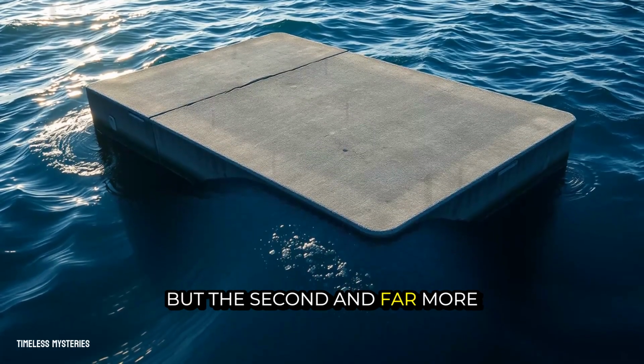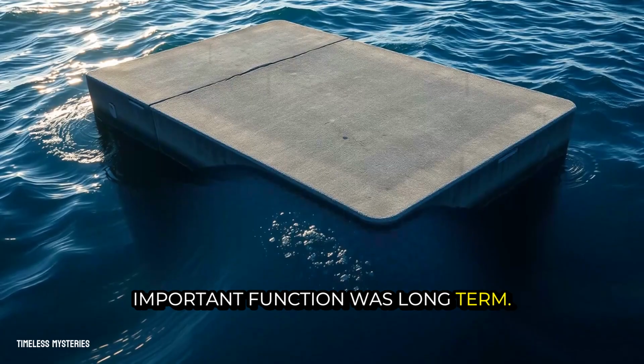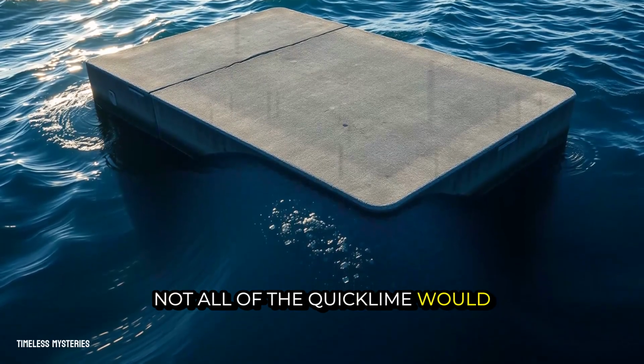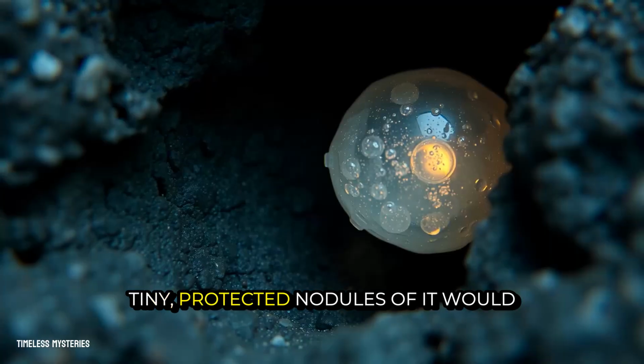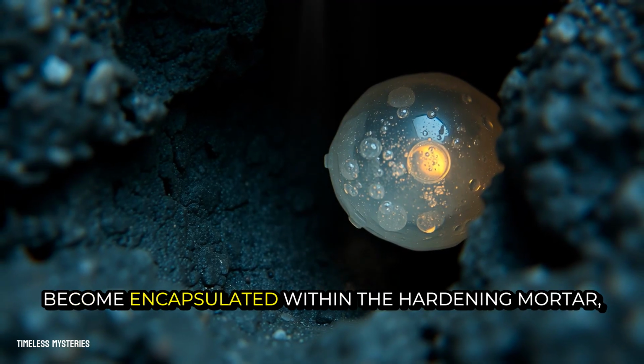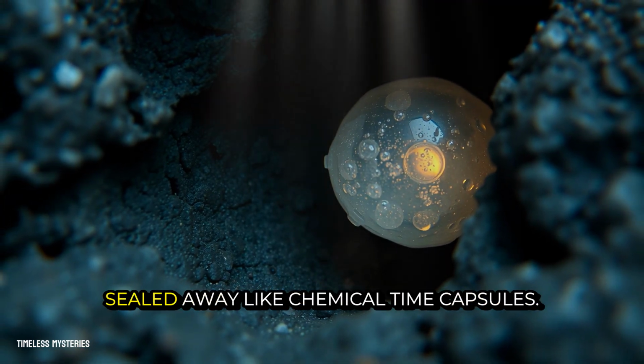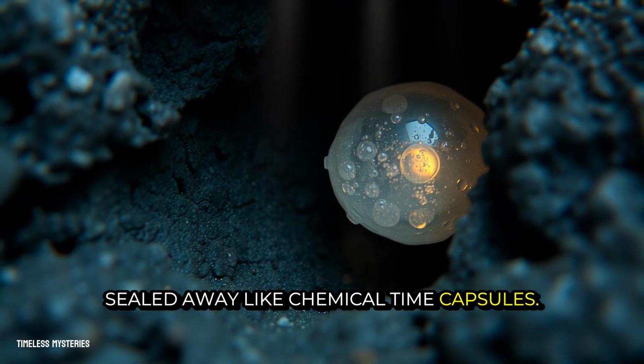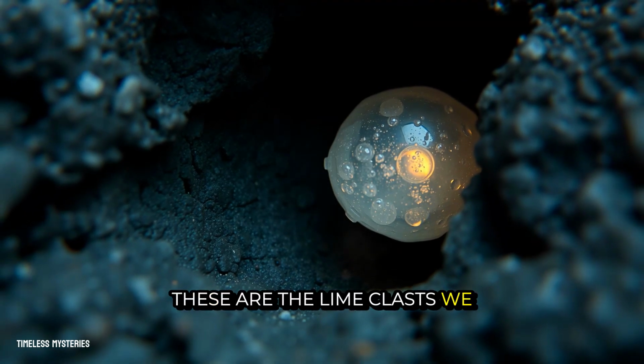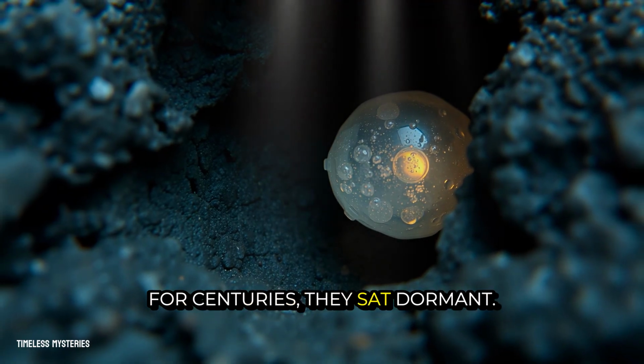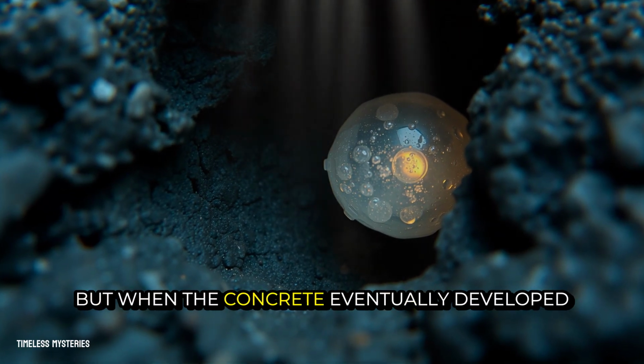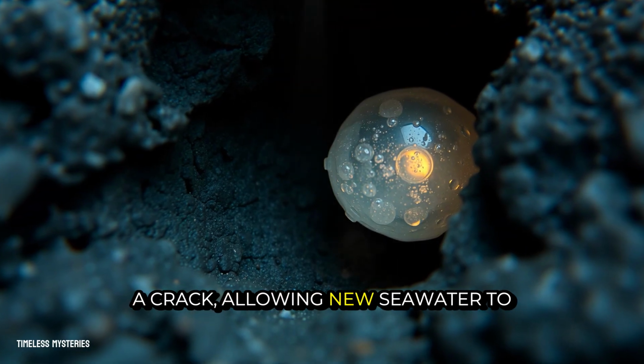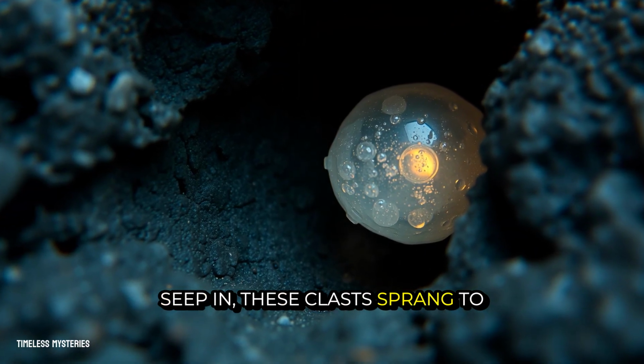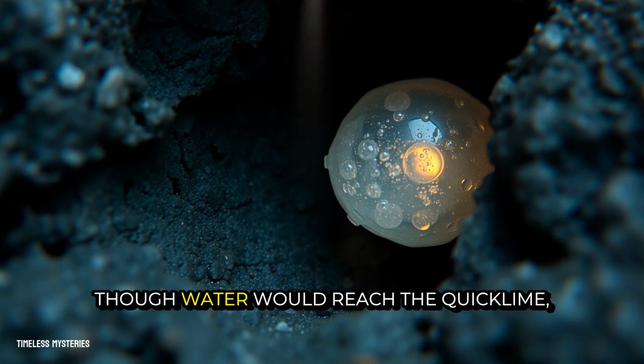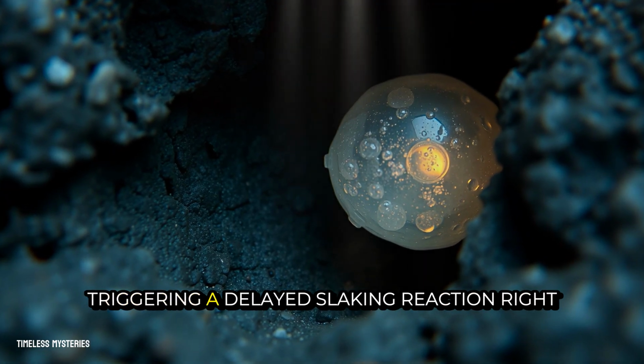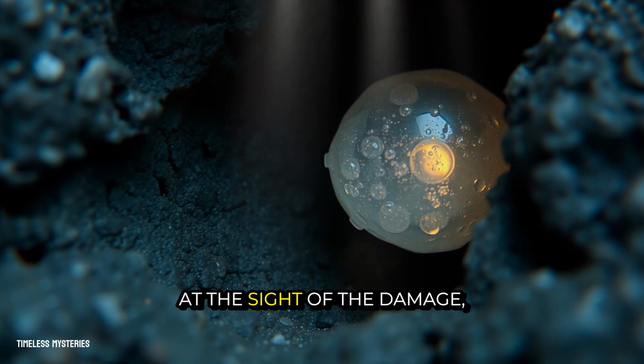But the second, and far more important, function was long-term. Not all of the quicklime would react immediately. Tiny, protected nodules of it would become encapsulated within the hardening mortar, sealed away like chemical time capsules. These are the lime clasts we see today. For centuries, they sat dormant, but when the concrete eventually developed a crack, allowing new seawater to seep in, these clasts sprang to life. The water would reach the quicklime, triggering a delayed slaking reaction right at the site of the damage.